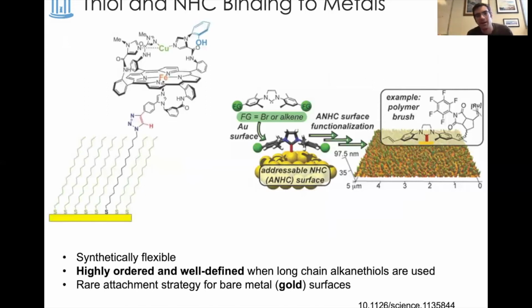Another classic attachment approach involves thiol binding to gold. This is, again, one of these classical surface modification approaches. You may have heard of self-assembled monolayers on gold, or SAMs, and that's been used as an approach to attach catalysts. One of my favorite examples comes from Coleman and Chidsey, who built this just extraordinary model of cytochrome c oxidase that has an iron center and a copper center and a phenol to model a tyrosine. And then they looked at different linkers attaching it to gold and varied the distance and the electronic coupling to this electrode, and investigated how that affected the oxidase reactivity.